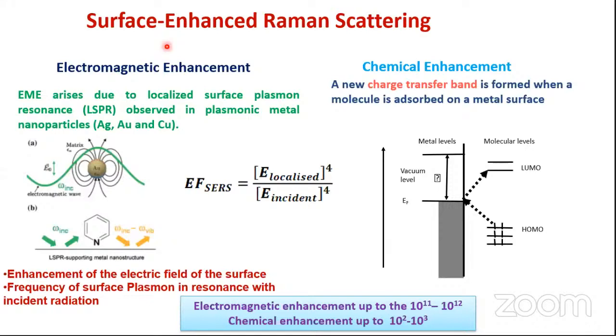That's what I said, SERS is surface enhanced Raman scattering. There are basically two mechanisms responsible for enhancement in the Raman signal. I already showed you where they put the pyridine molecule on a rough silver surface, and they saw that the Raman signal of the pyridine molecule was enhanced very much when the surface was rough. Now we know that there are two enhancement mechanisms: one is electromagnetic enhancement, the other is chemical enhancement.